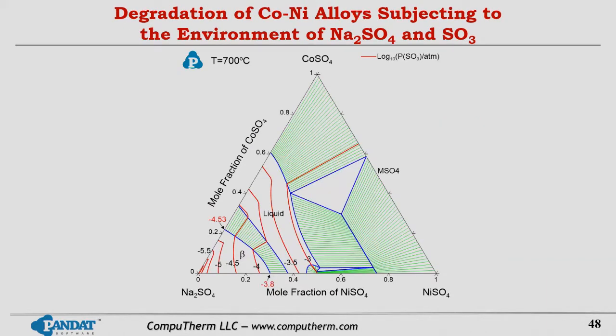However, what about if we add some nickel to cobalt, and how would the tolerance of the beta phase change? In this case, if we add 20% nickel in cobalt for this cobalt 80 nickel 20 alloy, we can calculate this highest tolerance of partial pressure increases a little bit. But if you add more nickel, let's say now we become a nickel alloy, nickel 80% and cobalt 20%, then the tolerance becomes even higher, which means nickel is more corrosion resistant in this application.